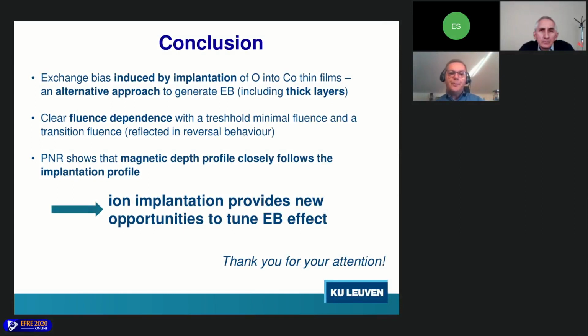So, in conclusion, what I hope that I've been able to convey to you is that by using implantation of oxygen into the cobalt thin films, this is an alternative approach to generate this exchange bias, even for very thick layers, which is not so easy with surface oxidation. And we've also shown that the materials modification is really mimicked by the magnetic properties. The Gaussian profile of oxygen ions is simply also determining a magnetic depth profile that is also Gaussian. We have seen and studied in detail the fluence dependence. I've shown that there is a minimal fluence before you see the effect.